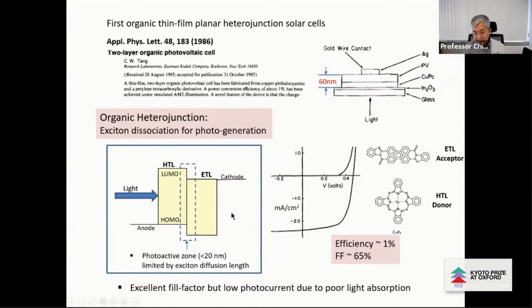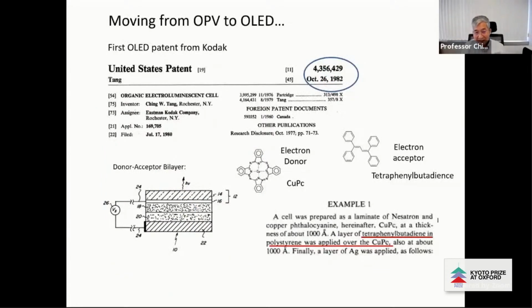But there's only one minor problem, and that is that the photoactive region is right at the junction. Beyond that, it's not photoactive because the electric field is very low. So there's no way I could improve the efficiency beyond this 1% with extremely thin films like 60 nanometers. There's not enough absorption. And that is the end of my research in organic photovoltaics, practically. So moving on, luckily there were organic light-emitting diodes. The first organic light-emitting diode I made at Kodak was again a two-layer structure with the copper phthalocyanine, borrowing from the solar cells.